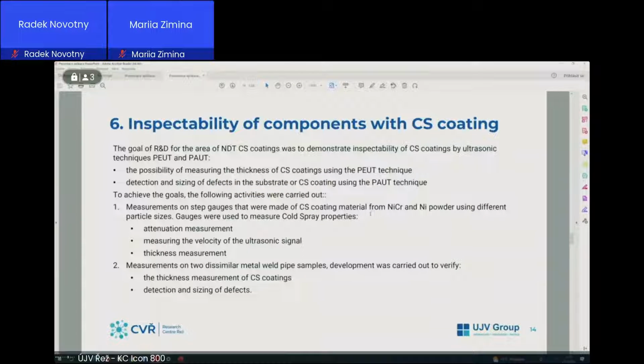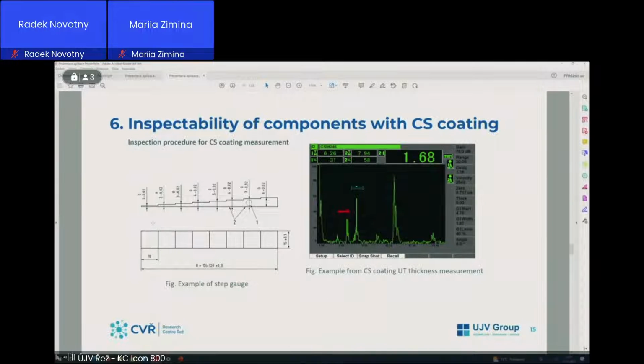Now let me speak about inspectability of components with cold spray coating. We used pulse echo technique and phase array technique. Pulse echo was for measuring the thickness and ultrasonic features of cold spray material. Phase array technique was used for detection of defects and for sizing of defects. We manufactured these step gauges. Here is a measurement of one step in this step gauge. And as I mentioned, these materials are good for inspections.